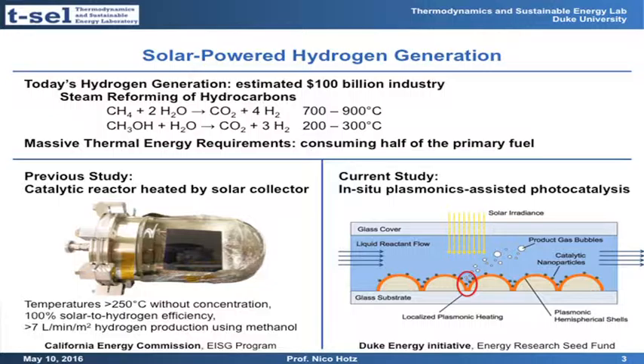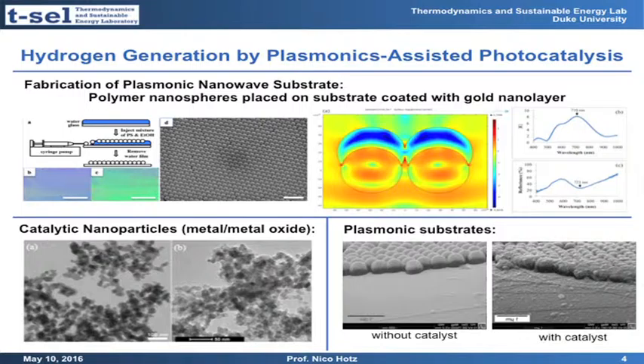We are at room temperature, but only locally down here we want to achieve temperatures that are high enough to drive chemical reactions, in this case, hydrogen production from methanol. The way we do that is we take these plasmonic substrates that we get from our collaborator, Dr. Bodin: polystyrene spheres on a substrate. They're 0.5 micron in size, coated with a thin layer of gold on top.